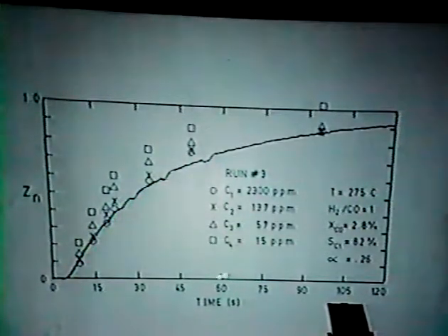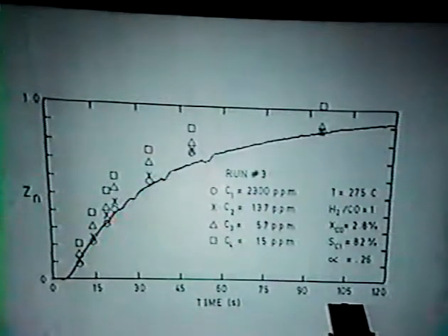And then we have the various hydrocarbons here. And you see, much to our surprise, that all the points don't lie on the line or below the line, they lie above the line. That is, as we go, for instance, here, we have methane and ethane, and propane and butane. That is C4, there's some ethylene in there. And these are the steady state quantities here, and these are the conditions over here, temperature, conversion, and so forth. Of course, this is a very poor Fischer-Tropsch catalyst, giving us an alpha of 0.26.